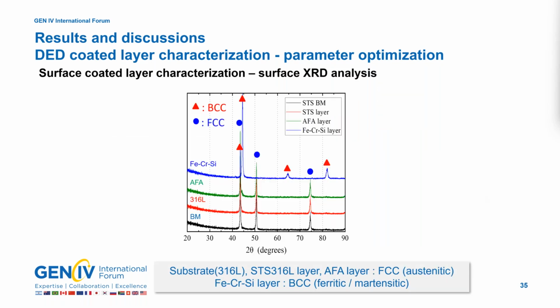The surface of the deposited layer was analyzed using XRD. As expected, the substrate, STS316L layer, and AFA layer showed the FCC austenitic phase. Additionally, the iron chrome silicon layer exhibited the BCC ferritic martensitic phase.